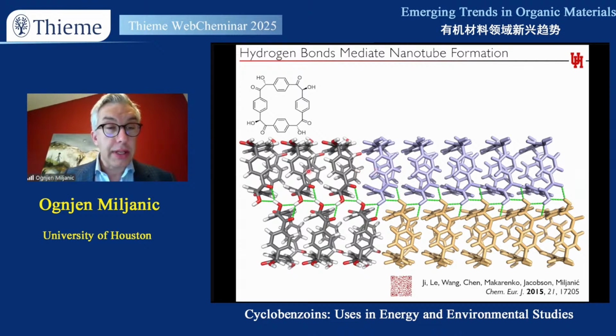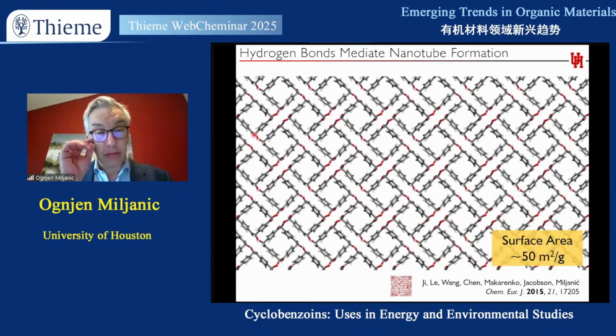But what is holding the nanotube together is, and so this repeats itself on each one of the 4 corners of this molecule. And so if you take these nanotubes and sort of turn them so that their opening will face you, this is what we'll see. And so this is not one layer of our structure, this is the whole structure. So it's perfectly aligned on top of one another. And because of this perfect alignment and the small cavity, we can detect a small surface area associated with these molecules, even though it's not very large. Now, this molecule, cyclotetrabenzoin, it had very pretty crystal structures and very nice to look at. However, for potential as a supramolecular host in solution, we really critically needed to make it soluble.